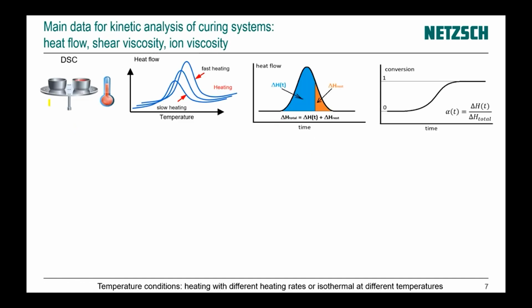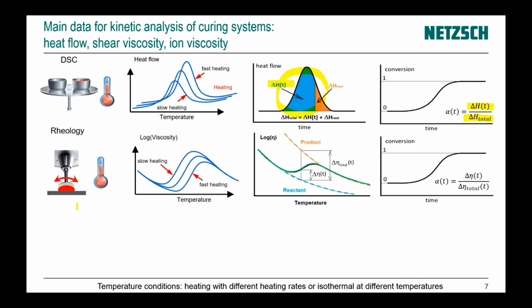Now, DSC: we have a sample and reference crucible, make heating and measure the heat flow between them. For the curing process the heat flow is a curve with a peak, and this peak means an exothermal process, the production of heat energy. Here we can measure at different heating rates, slow heating, fast heating. Then for each peak, we can create a ratio between the current peak area and the total peak area. This value is our degree of conversion.